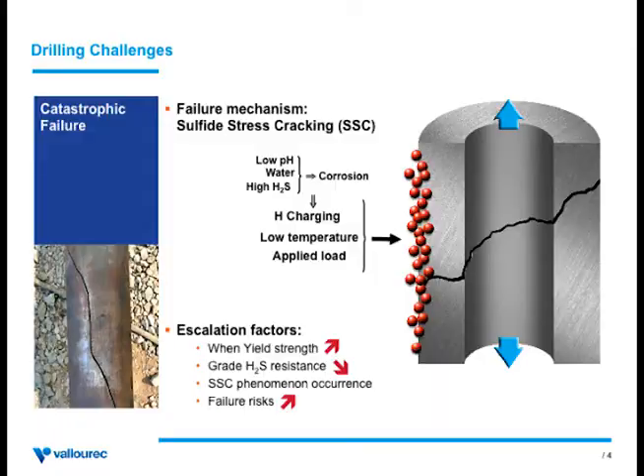Typically, the H2S will decompose at the surface of the steel, and you will have a hydrogen embrittlement of the material. It's very common to see pipes going out of the well after being exposed to H2S having a very dark green or black color. This is due to the first corrosion mechanism that occurs at the surface of the steel. Then the hydrogen will be present inside the steel matrix. If you pull tension on the material, there could be a crack initiation that could propagate in a brittle manner, again with a 45-degree angle, typically.